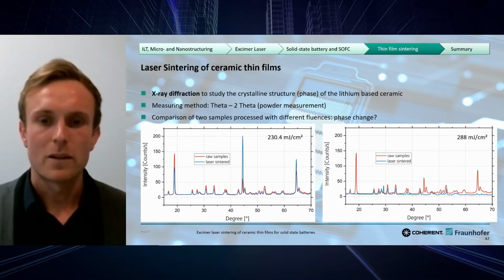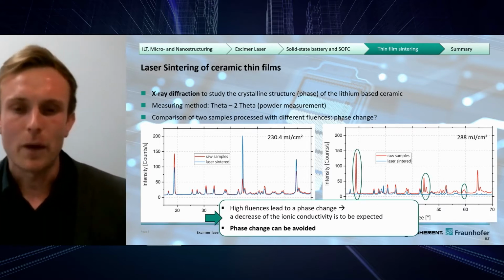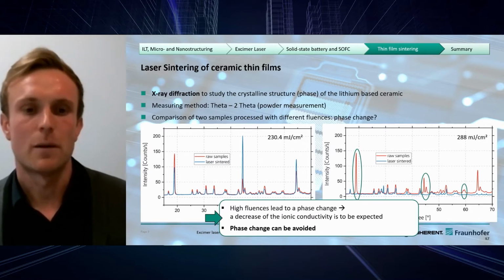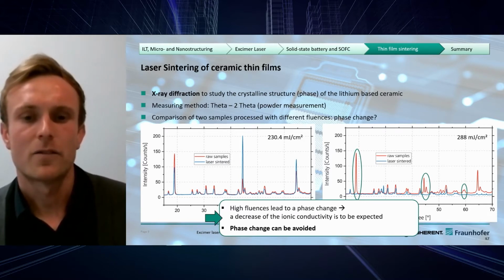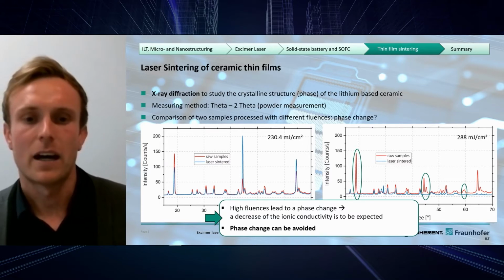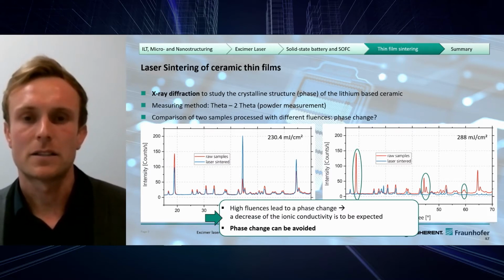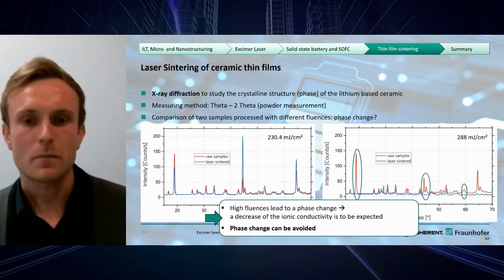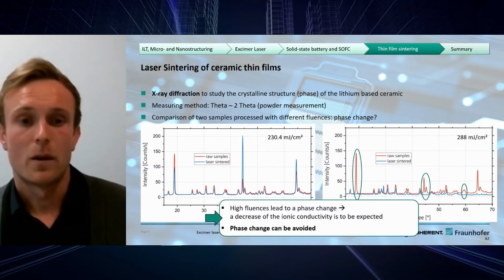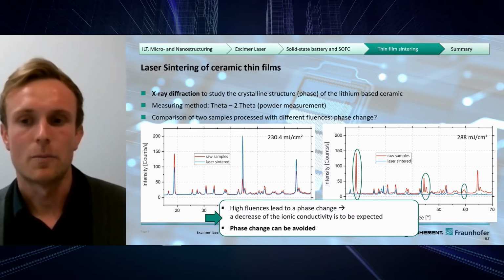But on the right-hand side, with the higher fluences, we can see that after the sintering process, some of these reflections are missing. So we can say that a phase change has taken place there, and it is to be expected that the ion conductivity will be less than before. On the other hand, we can say that with the sintering process, a phase change can be avoided. There's only a variation of intensity, which can be related to a rearrangement of the lithium ions to another lattice structure or orientation, but will not impact the electrochemical properties.